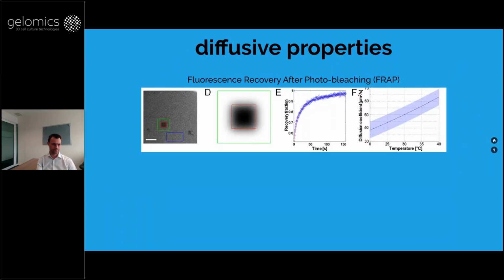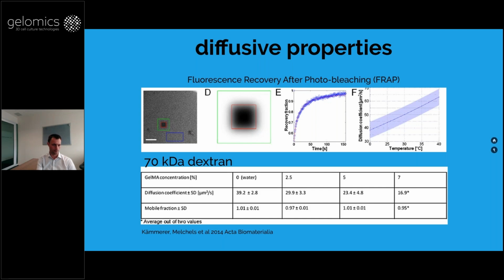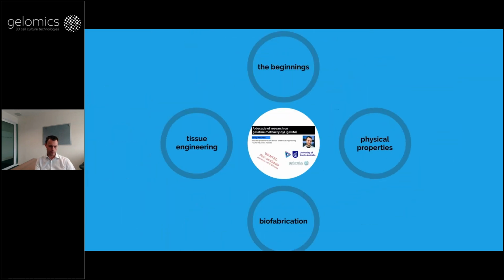We also looked at diffusion a bit longer ago through this FRAP process with a fluorescent FITC dextran. Dextran 70 kilodaltons is quite a big molecule. Despite that, we saw that the diffusion coefficients were quite high. So, for example, the 5% still diffuses at more than half the rate compared to still water. So really these gels, although they seem to be solid, because it's so much water, even big molecules diffuse really fast through it. So to those molecules, it's almost the same as being in water. So they hardly notice the polymer chains being there, which means that you can use this for 3D cell culture. So now we've looked a bit into those physical properties.